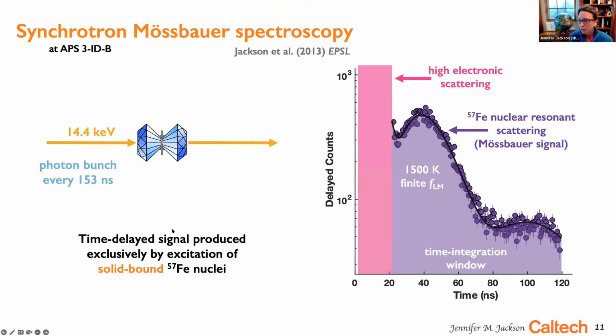So in the SMS experiments, the incident photons with an energy of 14.4 keV interact with the iron-57 atoms in the sample. And the time-delayed photons are produced exclusively by the excitation of solid-bound iron nuclei. A fit to the time spectrum constrains the sample thickness, among other properties. And during the melting run, we integrate the time-delayed photons over this shown time window, so as to conduct the experiments as fast as possible.